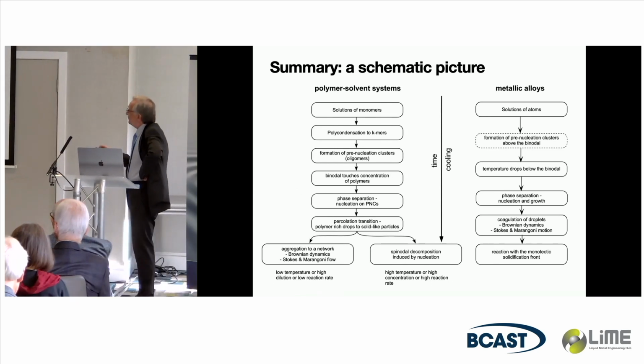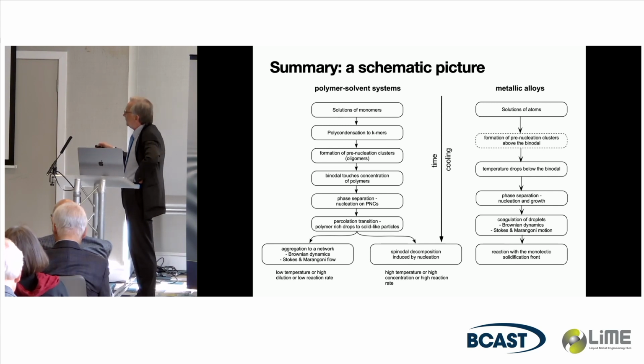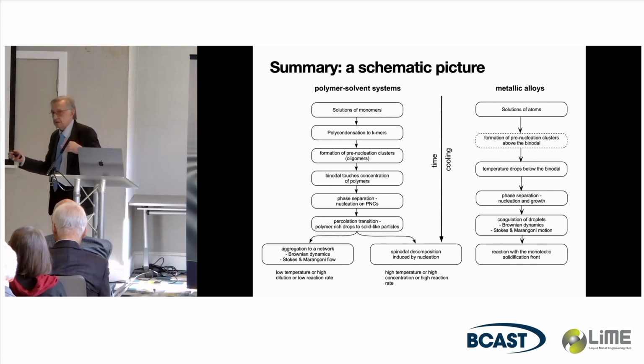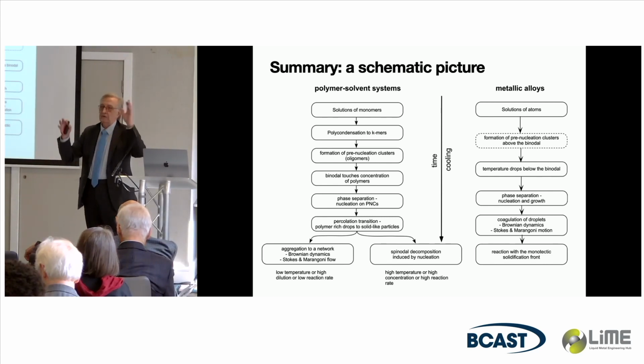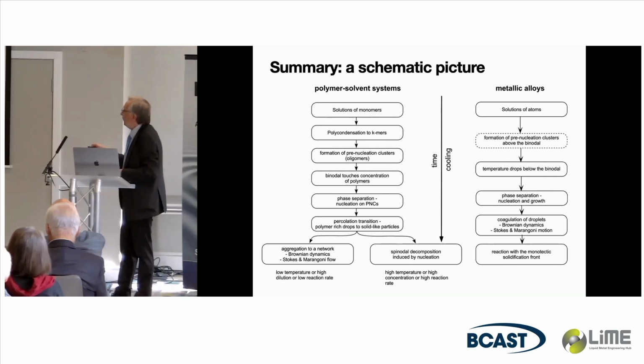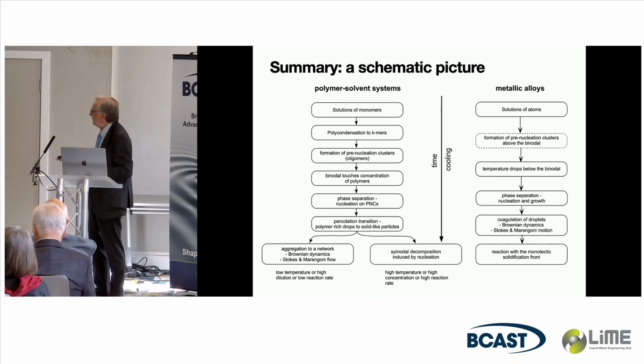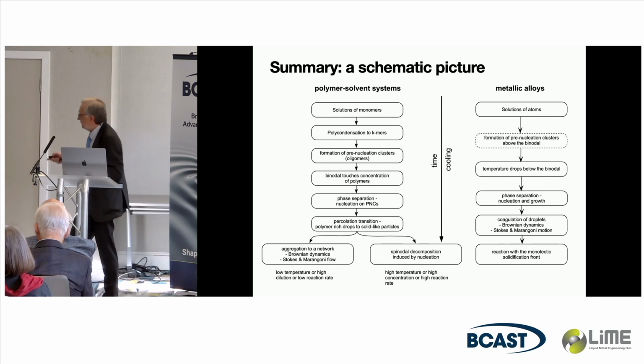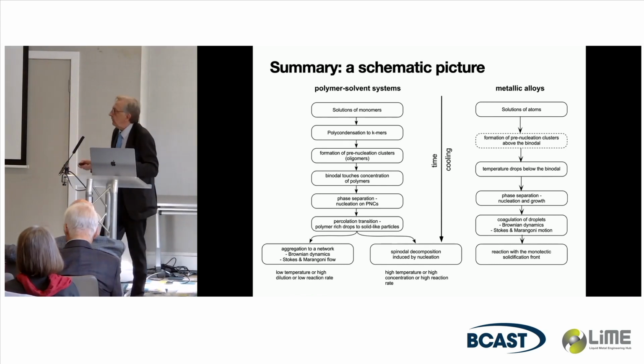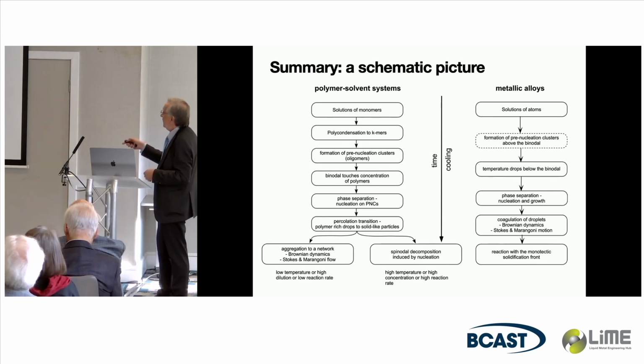So, summary is, the schematic picture for polymer systems would be solutions of monomers, polycondensation or polyaddition to oligomers or k-mers. You have formation of pre-nucleation clusters because there is no need for heterogeneous or homogeneous nucleation. You have already a lot of polymers with different degrees of polymerization in the systems. So once the binodal touches the concentration of the polymers, phase separation sets in, probably on these pre-nucleation clusters, and depending on the concentration, you might have spinodal decomposition, this was observed, or aggregation to a network. If you look at alloys, that's the same, solution of atoms. I come to this in a second.